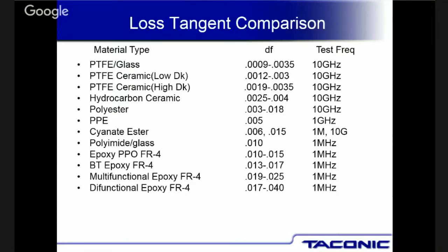When you look at it, with a dissipation factor of 0.0009, that means that the fields that are going through the material, you're only losing 0.09% of the signal or the fields going through the material. By the way, where does that go? It generates heat. It's one of the losses that you'll find. When you start sticking other things into pure Teflon, the losses go up a little bit because you're sticking something else in there. So when you go into the second one down, PTFE ceramic, you can see that the losses go up where you're now losing 0.12% of the fields through the material.